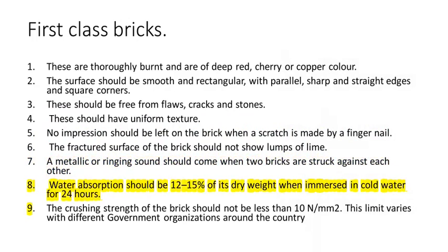8. Water absorption should be 12 to 15% of its dry weight when immersed in cold water for 24 hours. 9. The crushing strength of the brick should not be less than 10 N per square millimeter. This limit varies with different government organizations around the country.